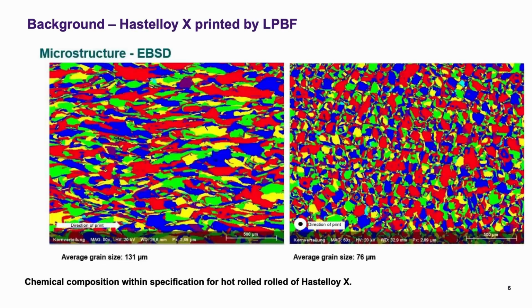And if we go to the LPBF printer then, because that is the additive manufacturing method we use, laser powder bed fusion. We can see, as we've seen also in previous presentations, that we get the columnar grain structure and the highly anisotropic properties. And the chemical composition is within the specification for conventional Hastelloy X, but one difference is that it typically has a significantly lower carbon content. In the rolled Hastelloy X, we only have a maximum limit on the carbon.